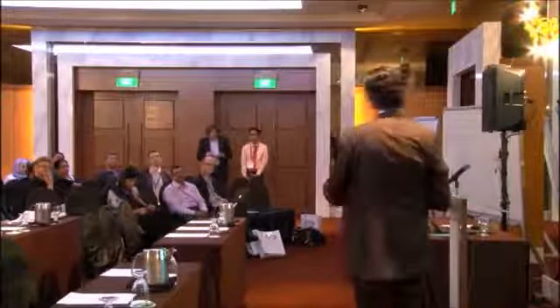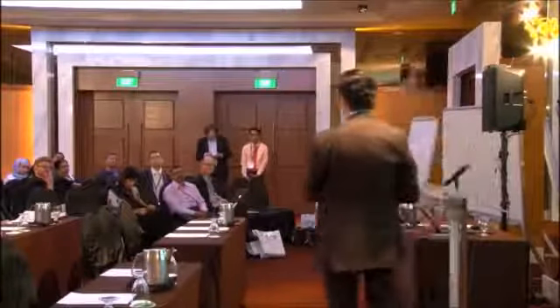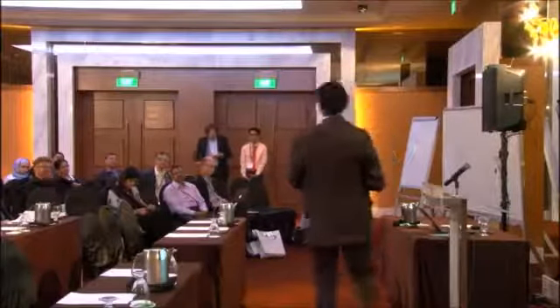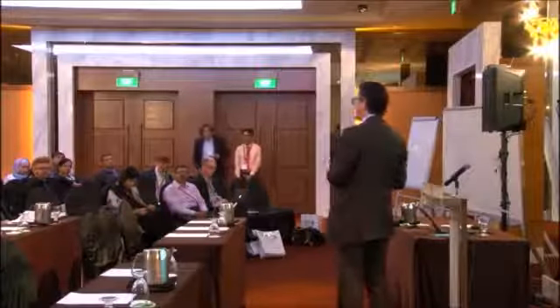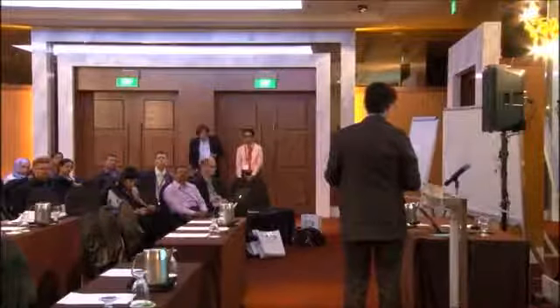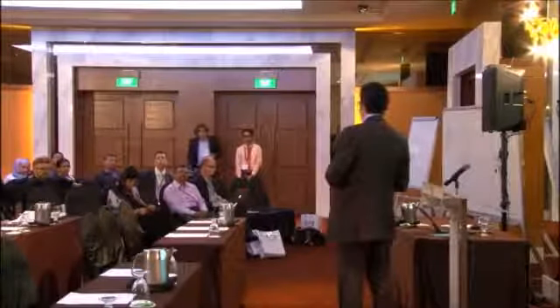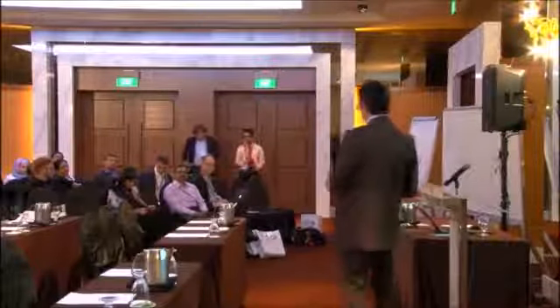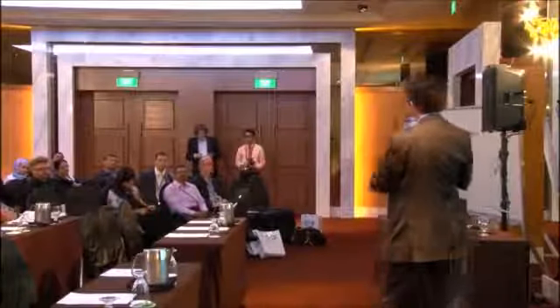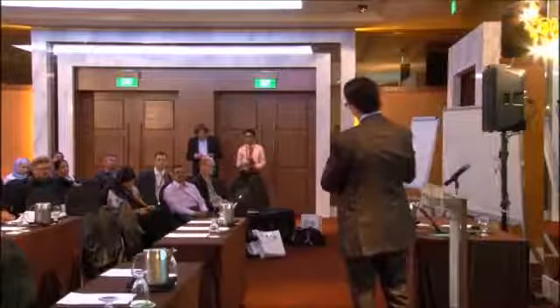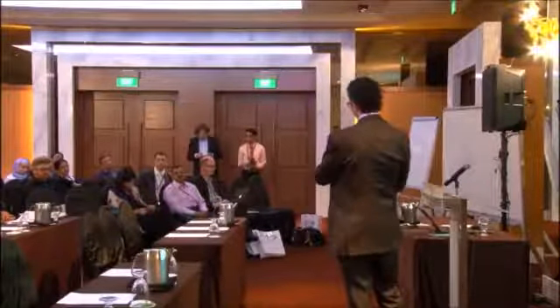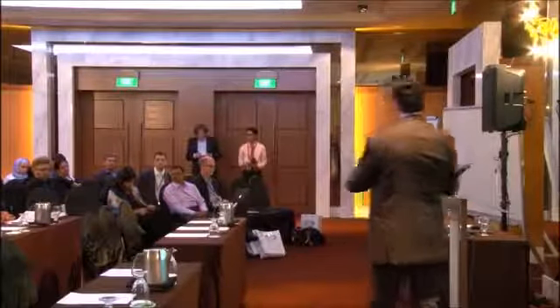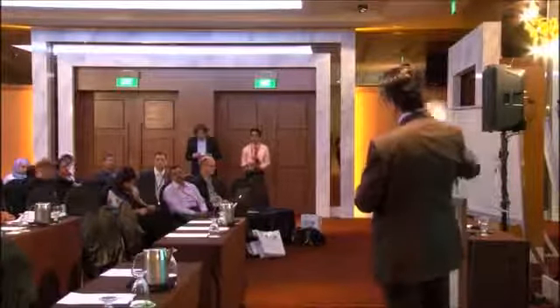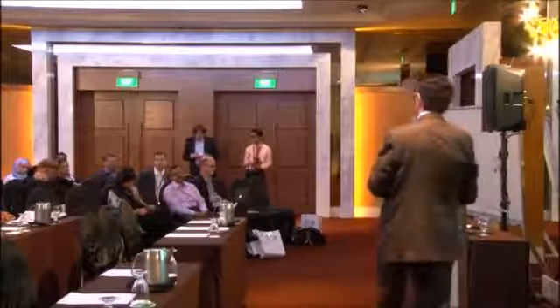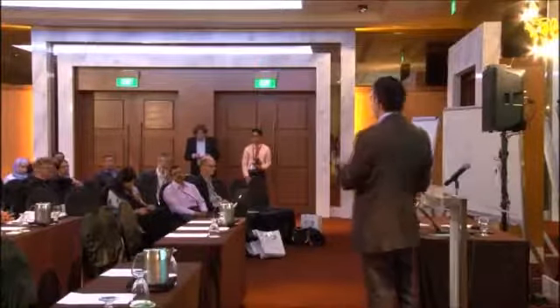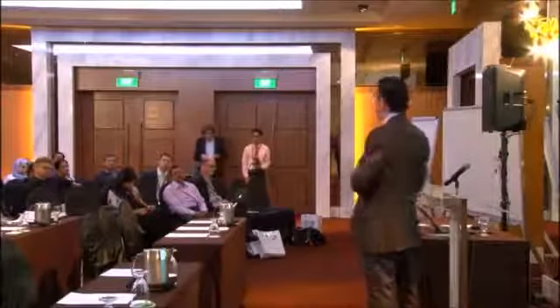If you measure, I need glasses to see any elongation in this material. It's about, I don't know, maybe 0.1 or 2%. Yeah, so it's quite stiff. That's why it's connected with the high steel grade rod, and the ductility is given in the surface between the rod and the ductile ring. Because there's no bending, nothing in this material.